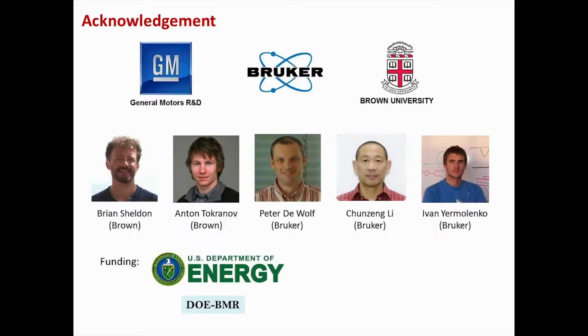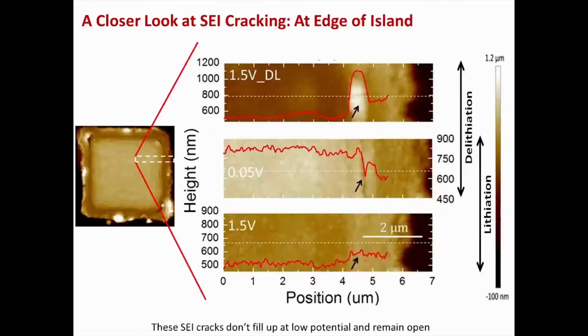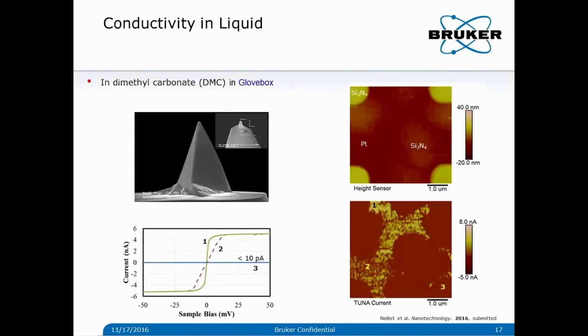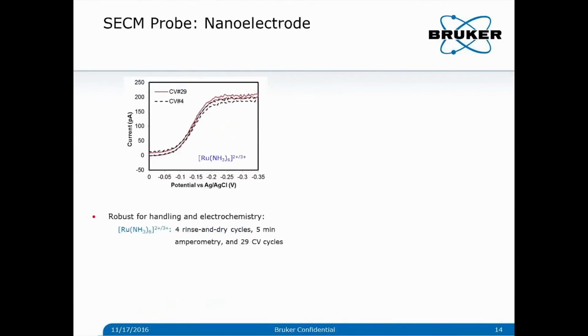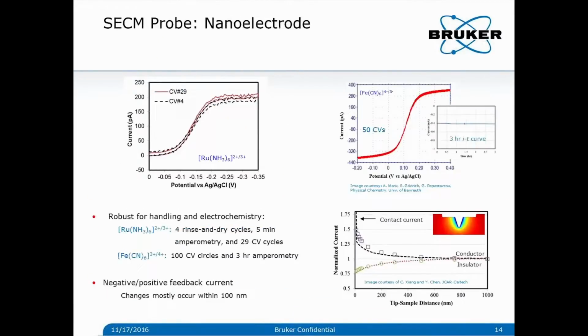This one seems to be for Teddy. How does the resolution, for example, current, height of the tip behave with time? For example, its stability, does it change much? So let's talk about the resolution first. I showed you the theoretical simulation showing the compact diffusion layer. Its thickness is actually less than 100 nanometer, or you can even say 50 nanometer. So it has the possibility to achieve about 50 nanometer resolution, and we did see that from our experiment. Normally, I have several examples showing a resolution of less than 100 nanometer.